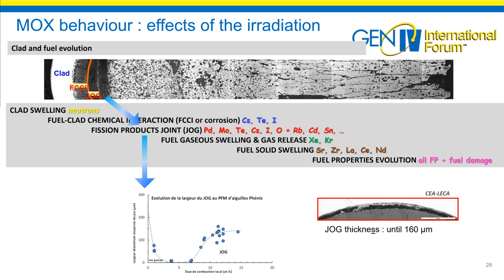29. So in parallel, we have some fission products like cesium or molybdenum that diffuse until the clad pellet gap to form the so-called oxide joint, or jog in French, composed of several fission products forming oxides. So mainly it is Cs2MoO4 and Cs4MoO7. So the jog can reach 160 microns of thickness in the case of low clad strain, but it's even larger if the cladding swells much more. So it will lead to an improvement of the thermal behavior of the pin, with a quite low thermal conductivity, but much higher than a gap filled only with gas.